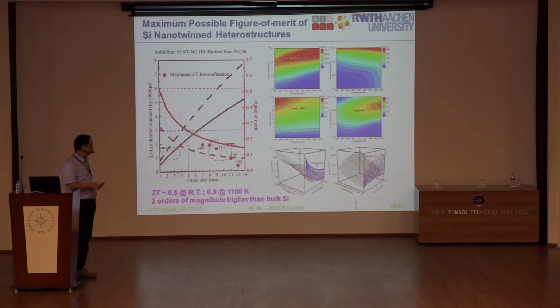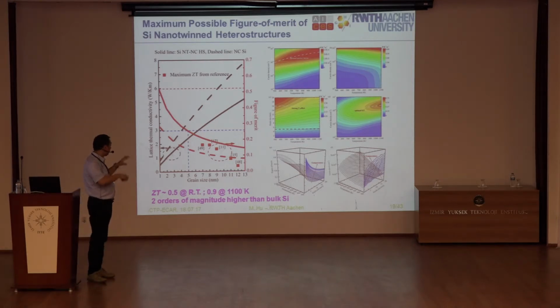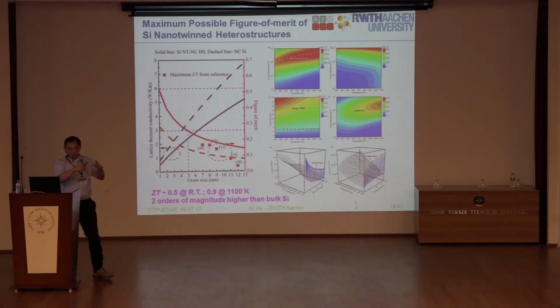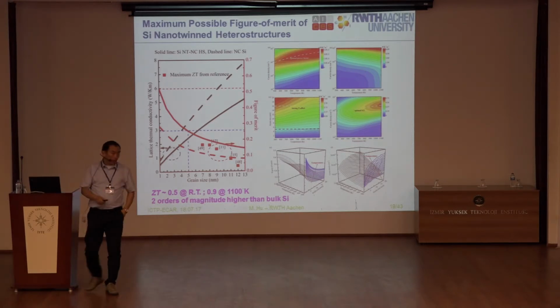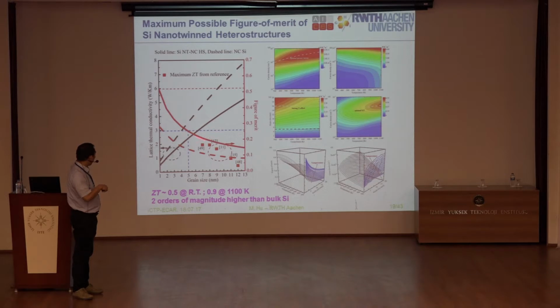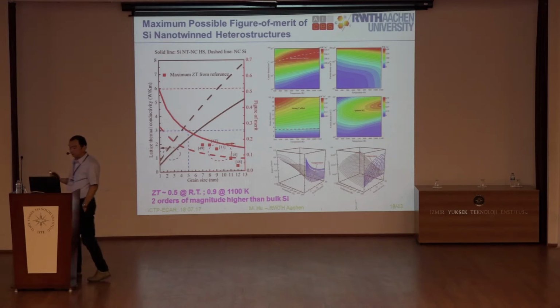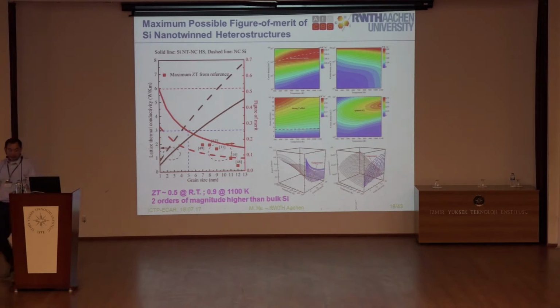So eventually you can play with the different doping concentrations, and also play with the polycrystalline grain size and the figure of merit. Eventually you can reach about 0.5 at room temperature and then 0.9 at 1100 Kelvin. So this is the maximum ZT coefficient that can be realized for silicon, and if you compare with the literature and with the experiments, this is the highest value we can reach for bulk silicon. So it's bulk-like, but it's polycrystalline, and also inside the polycrystalline you can introduce this nanotwin.